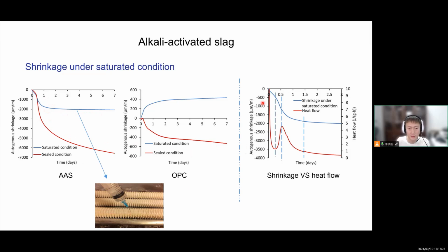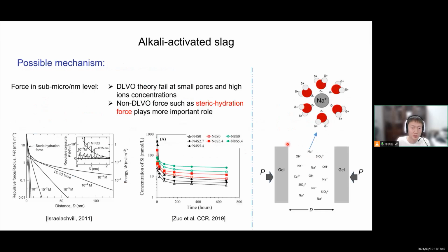And then we correlate the autogenous shrinkage in the very early age with the heat flow, which indicates the reaction rate. We can see they correspond to each other very well. So in the dormant period, there is a small autogenous shrinkage developing, and during the acceleration period, the shrinkage increases very fast. And during the deceleration, the rate becomes more stable. So we hypothesize the reason is not just the reaction rate, but the consumption of ions.